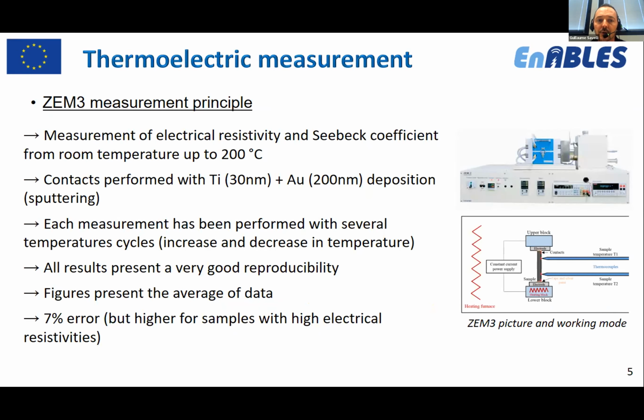For the thermoelectric properties, we use ZEM3 measurement principles. So you can see the tool in the pictures. With this tool, we can measure the electrical resistivity and Seebeck coefficients from room temperature up to 200 degrees Celsius for thin films.